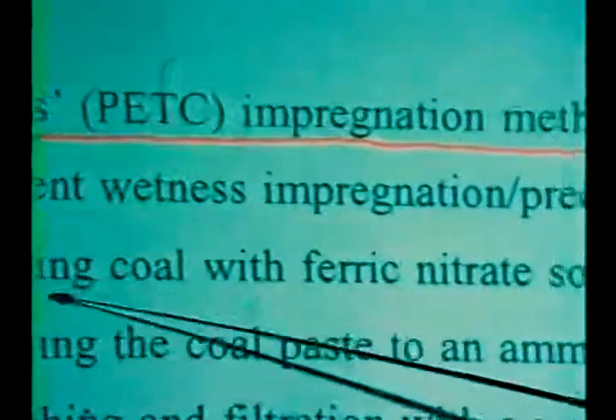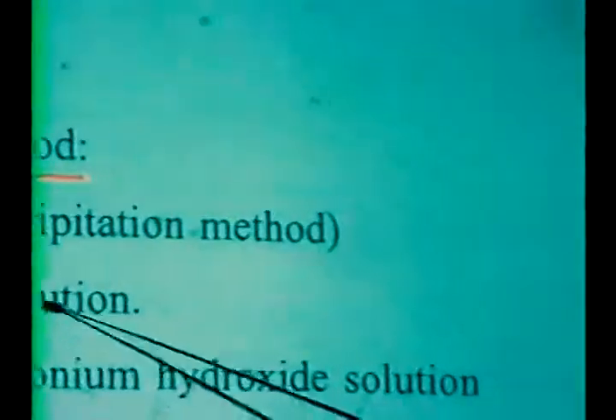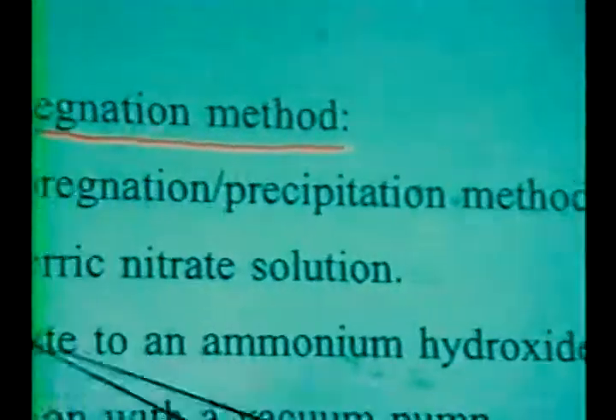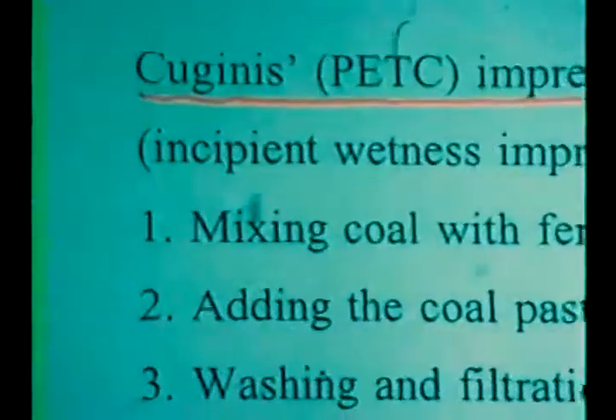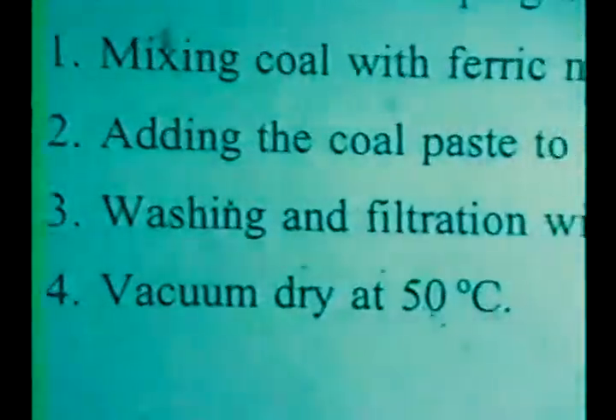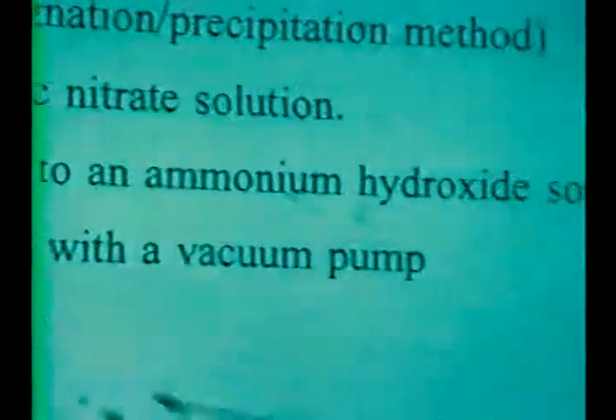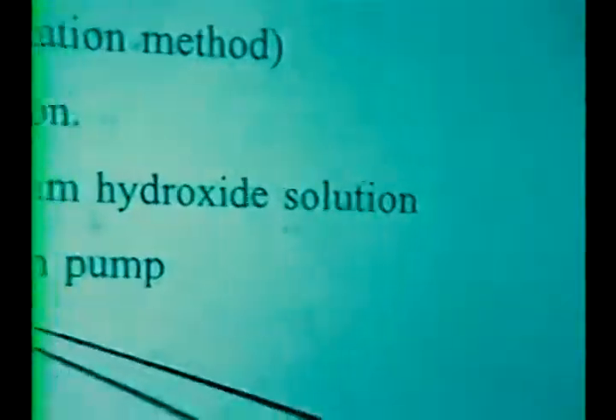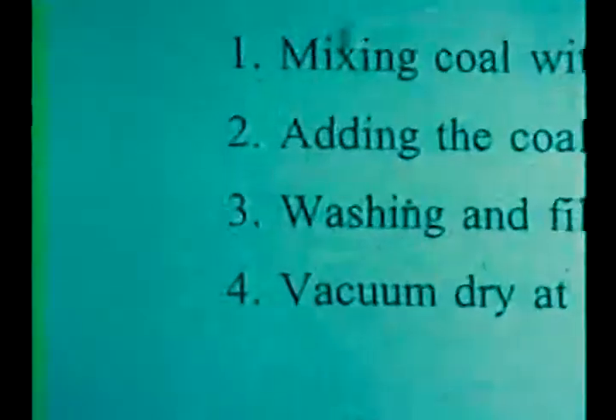First, they mix the coal with ferric nitrate solution, and then make a paste, and then put the paste into an ammonia hydroxide solution, and then wash and filter with a vacuum pump, and then dry.